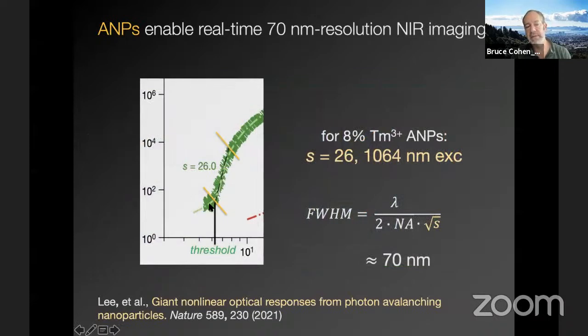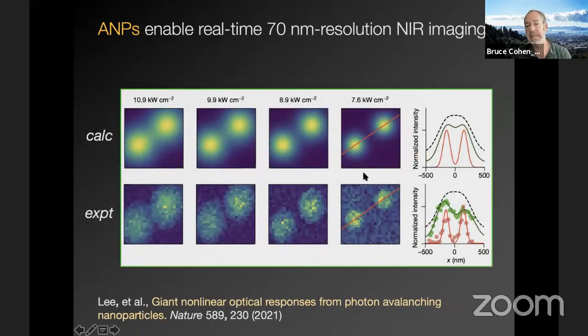It's not as steep either before or after this threshold event. So you would expect, actually, at higher powers, you would get worse resolution, and that's what we're seeing here. You can see this is the lowest power I'm showing you, and this is a slightly higher power, and the resolution actually is better at this lower power because we're at the threshold.